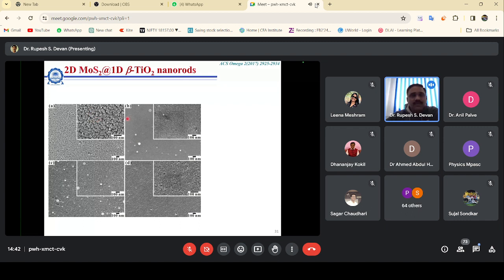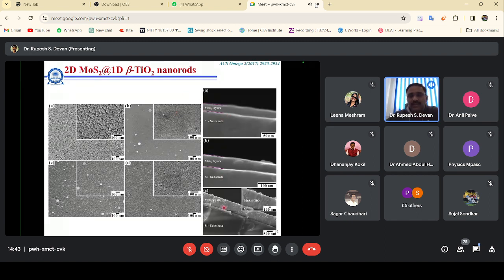Later on, these 1D structures were decorated with 2D structures. We can see here these nicely grown 1D nanorods, TiO2 nanorods. And on top, we decorated these nanorods using 4 nanometer, 20 nanometer, and 40 nanometer thick layers. When the 4 nanometer layer is there, as I mentioned earlier, the nanorods can act as a very good template. Because of that, these 2D structures are nicely decorated, maintaining the one-dimensional morphology. When you increase the thickness to 20 nanometer, the top portion is accessible to the 2D structure, and they grow like particles. And when we exceed this to 40 nanometer thickness of MoS2, then uniform layer decoration of the 2D MoS2 is formed. When you check the cross-sectional view, you will realize that for 40 nanometer, all the gaps were filled and a thick layer was formed.